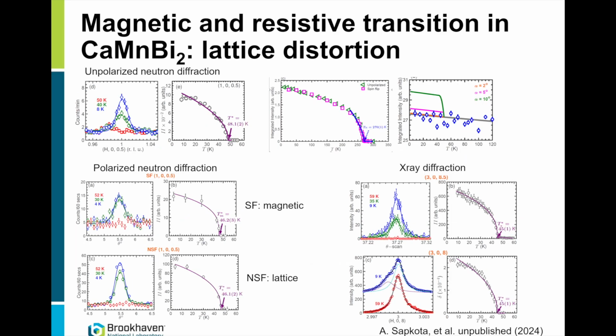All right. So what's happening at that temperature? Well, what's happening is that we observe a superlattice peak, first in unpolarized neutron diffraction. This is a superlattice peak corresponding to doubling of the unit cell in the C direction, so doubling of the layering. That peak has both magnetic and non-magnetic components. It is also seen in X-ray diffraction, of course, because it has a lattice contribution. But in addition to the doubling of the unit cell, X-ray diffraction also shows that there is an orthorhombic distortion in the plane. So there is a structural transition at this temperature.